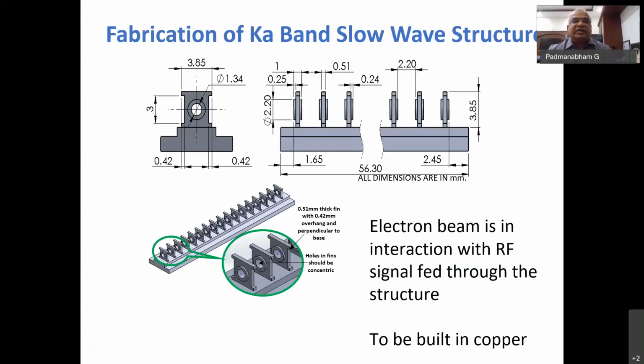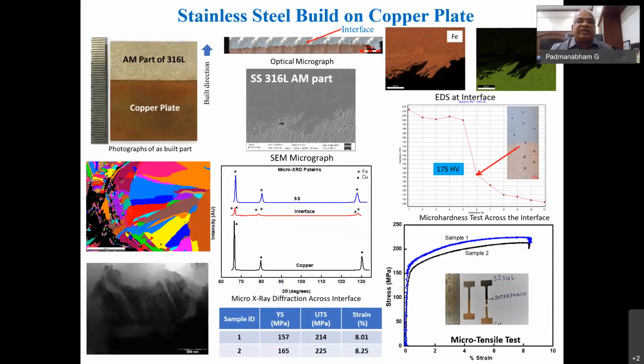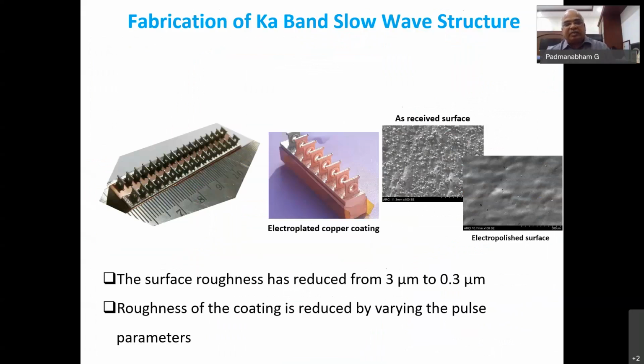So what we did was, first did experimentation in terms of building the features with the more friendly 316L on a copper plate. Did all the mechanical interface or metallurgical interface studies and the mechanical property studies, found that it is mechanically good, and then took a copper block and built the steel features onto it, and then electropolished it and got the component that we are looking for. So this is what I call hybridization of the additive manufacturing methods.